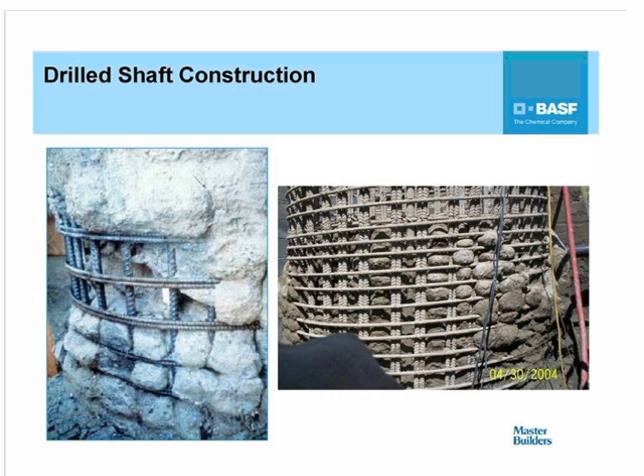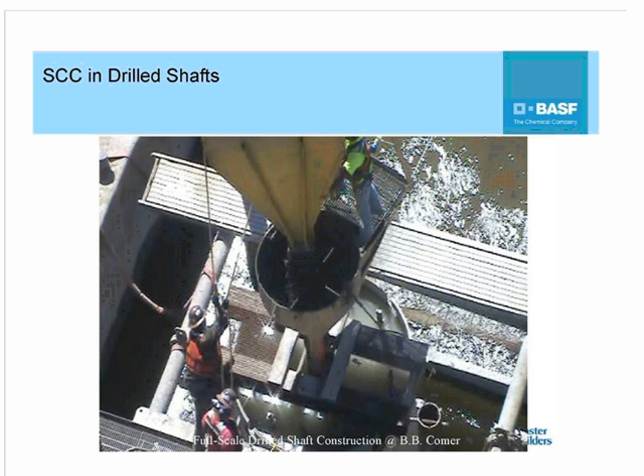Another area where self-consolidating concrete is being adopted, especially by a lot of state agencies, is in drilled shaft construction. And this is because with the change in detailing to accommodate seismic activities and so on, the hoops are now much tighter. So even with the use of just normal superplasticized concrete, the typical 8 to 9-inch slump concretes, the concrete may not necessarily flow out of the cage, resulting in the photographs that we see on the screen now. With self-consolidating concrete, it's been shown that the concrete can rise uniformly within the shaft, because of the high fluidity of the mix, resulting in very, very few defects.